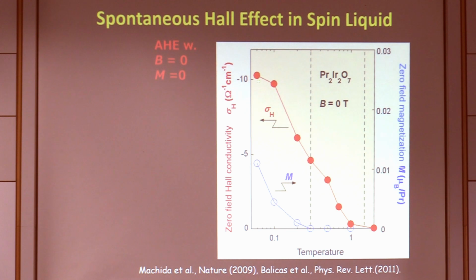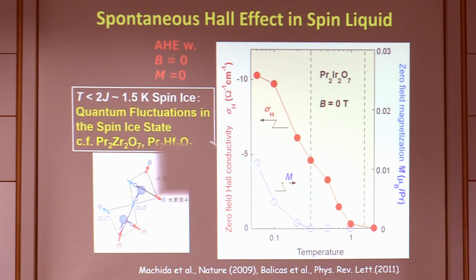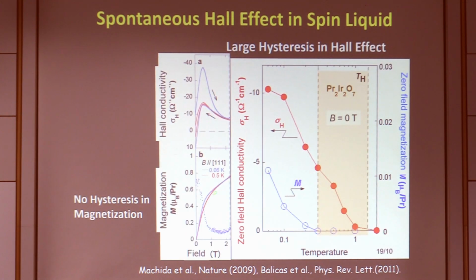And when we cool down the system, we found that the Hall conductivity goes up, something you find in a ferromagnet. Nonetheless, magnetization remains either zero or very tiny, of the order of a few 0.01 mu B per magnetic moment. And this is actually what we know as a quantum spin ice state, which is one kind of quantum spin liquid. So this can be viewed as a chiral spin liquid.